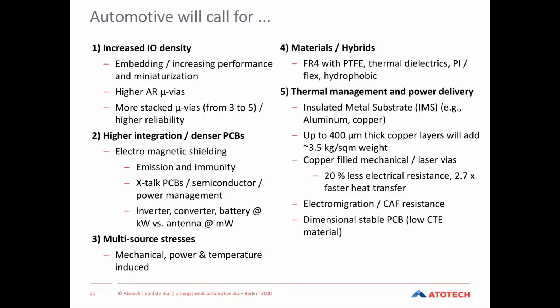And in general, there's the need for better heat transfer. For example, what I mentioned is copper through-via filling. Another one, conductive anodic filaments will become more prone due to materials capable of handling high voltage or high TG. And those materials are typically more brittle. So there's a high risk with conductive anodic filaments.